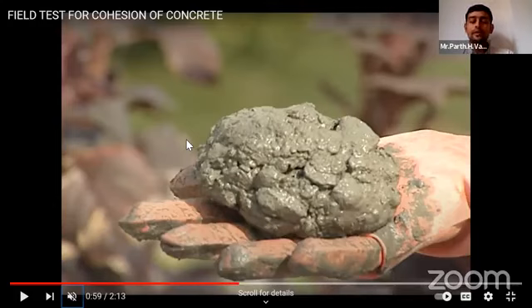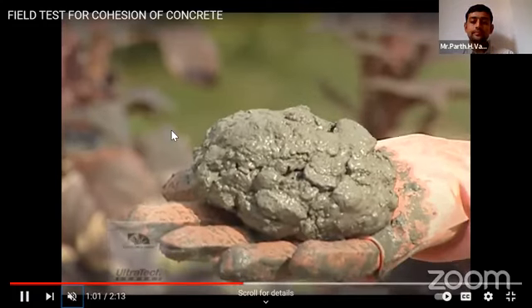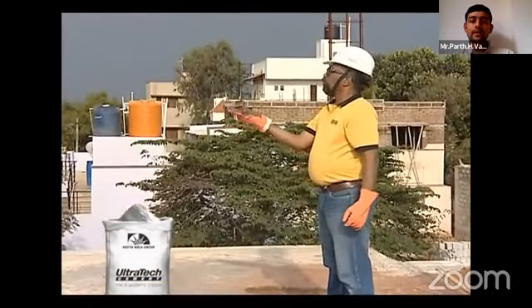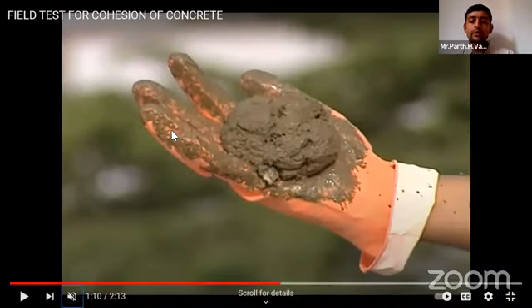And if the concrete looks even worse than this, then more problems are there. We can even say that our mixing is not proper, meaning the ratio of the aggregates is not proper either. Then another thing: if we throw it from around 2 feet of height, it should have cracks. The last time I said that it should not have cracks, but this time it should have cracks, as we increase the height from 6 to 8 inches to 1.5 to 2 feet. If it cracks like this and has minor cracks, then the concrete is cohesive.